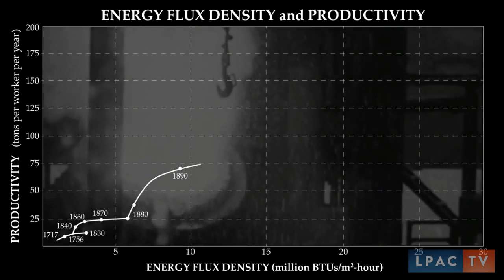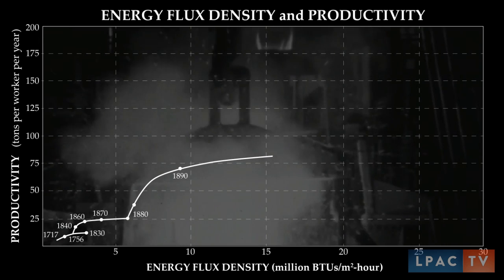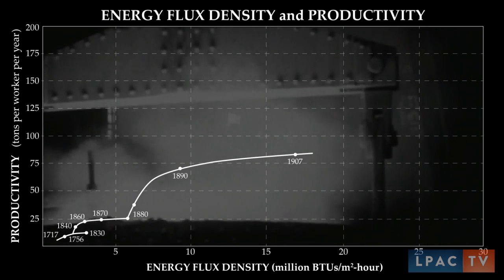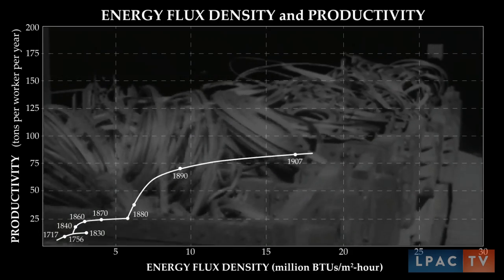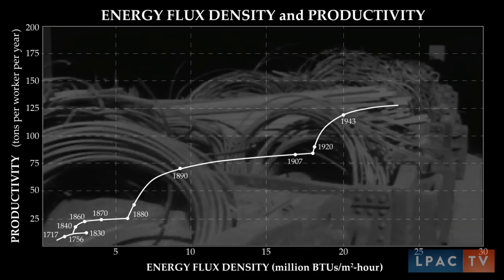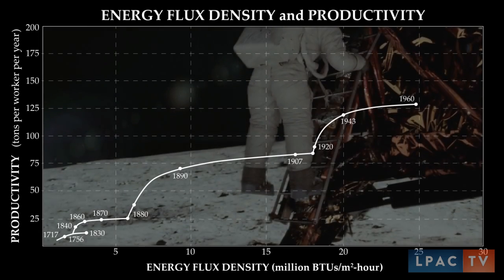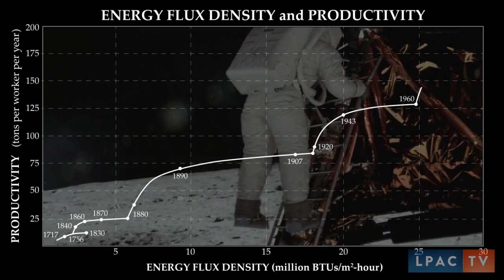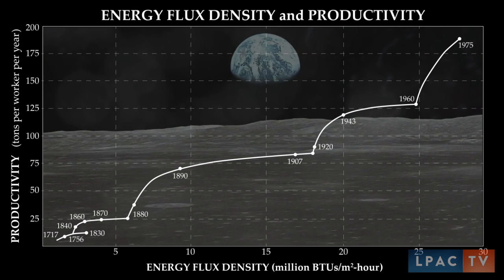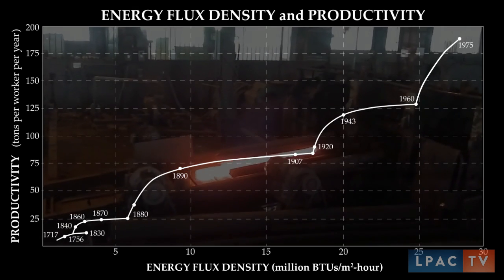Through the 1880s and into the beginning of the 20th century, the introduction of even hotter burning coke and a preheated blast of air drove both the energy flux density and productivity up another threefold. The next leap was spurred by the needs of the World War II mobilization, resulting in the introduction of pure oxygen to the furnace, as well as prefabricated iron pellets. The last leap was driven by NASA's Apollo program, bringing in the precision control and other improvements made possible by computers, culminating in an energy flux density 10 times higher and productivity 20 times higher than that of the early charcoal furnaces.